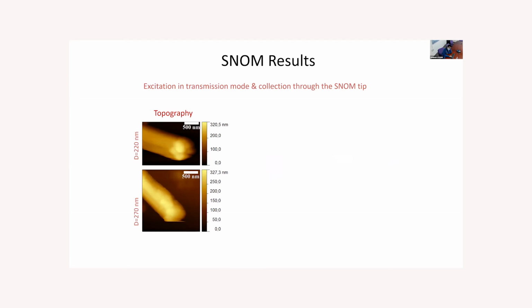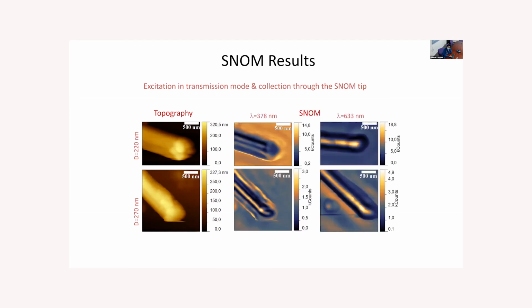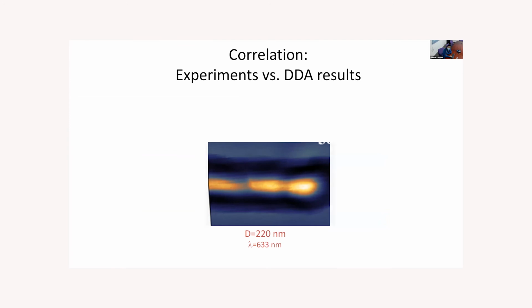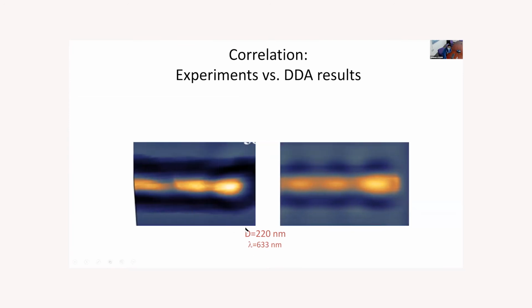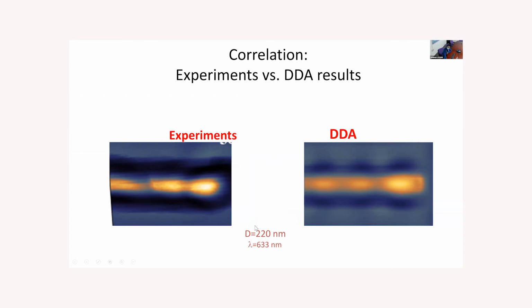They did a very good job, and they got this beautiful image of the whispering gallery modes of the single nanowires. Here you can see the topography of the samples. Using two different wavelengths, you can see two nanowires with different diameters, and you can see the near field distribution in this system. After that, we performed some calculations, and happily we found that we were able to model the experiments in a very good way.